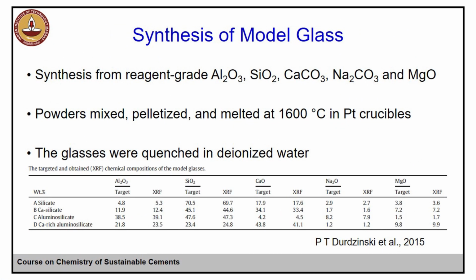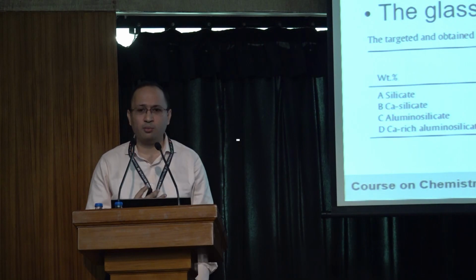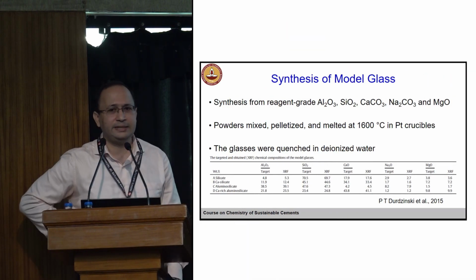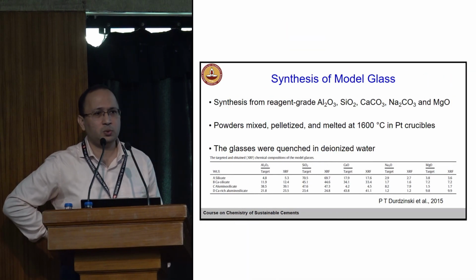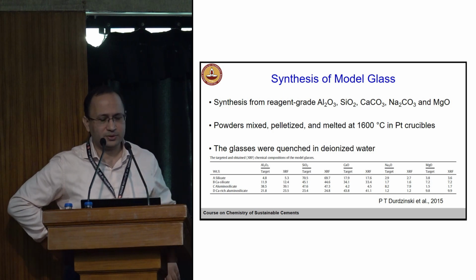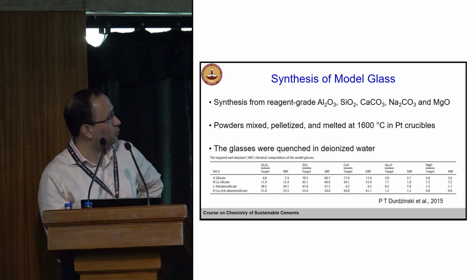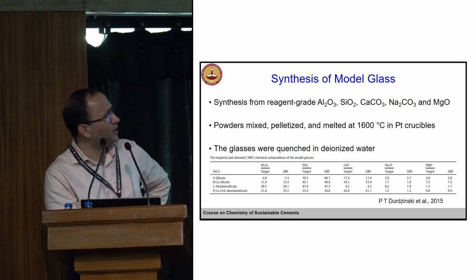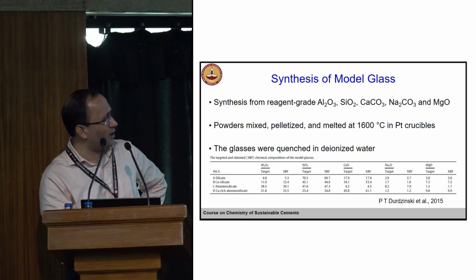Those of you who are interested can go through this work done 10 years back. They looked at model glass. Because of the variability we see in these materials, the first thing is to synthesize these model systems of different compositions. In this study, they looked at a synthetic system which has these components, and we can vary the composition. For example, it was primarily silicate, then you had calcium silicate.